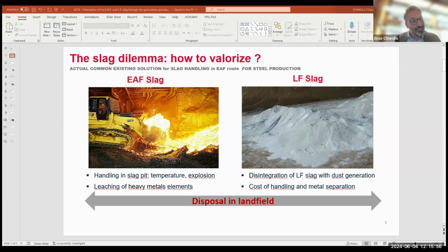We avoid the dust production, reducing the cost of the slag handling because we avoid the disintegration, and we stabilize even the elements, avoiding leaching, in particular in the case of the heavy metals. The dry granulation will also permit us to avoid the use of water, which allows us to avoid the emission of gaseous pollution that could be toxic for workers and further people working in the surroundings of the slag management.